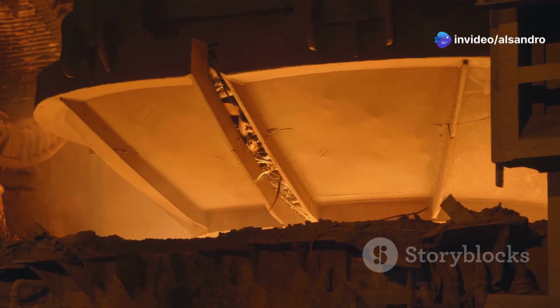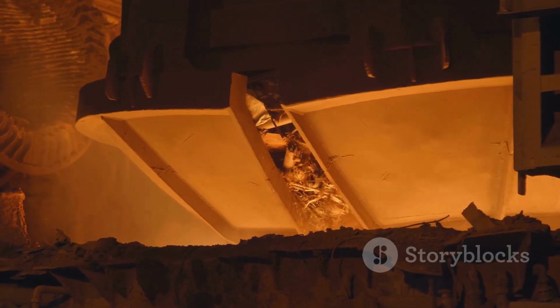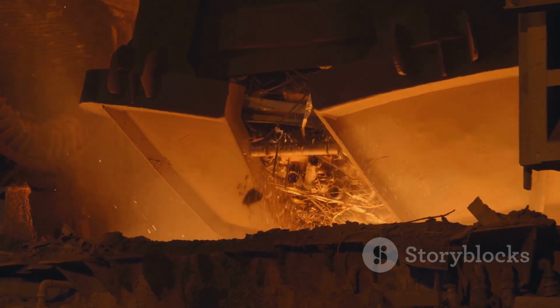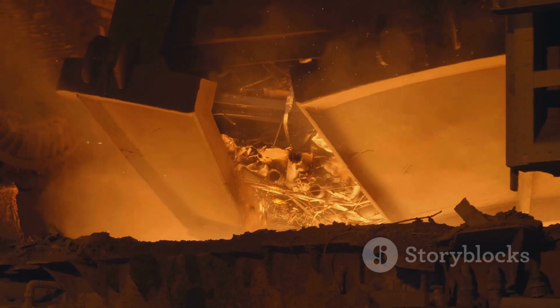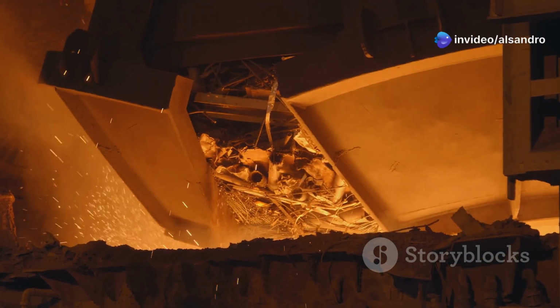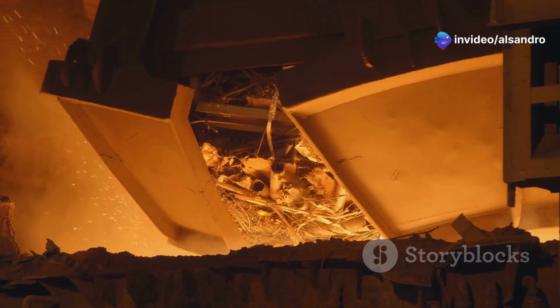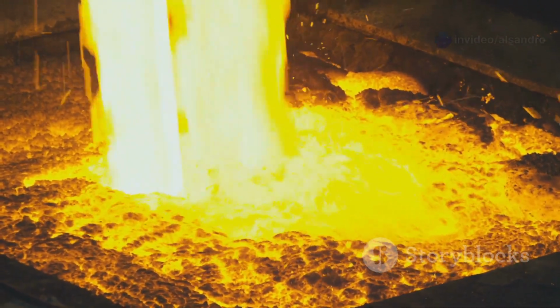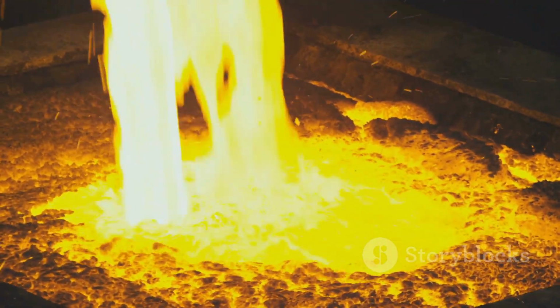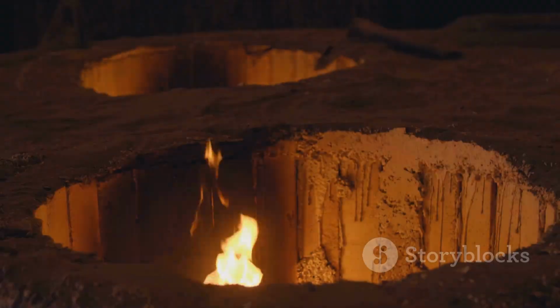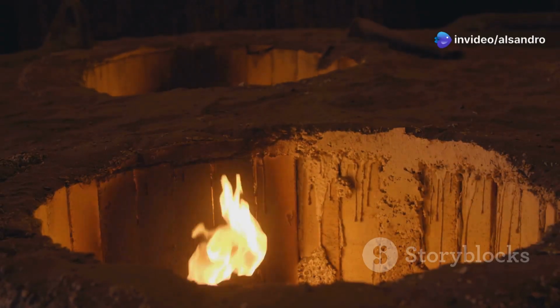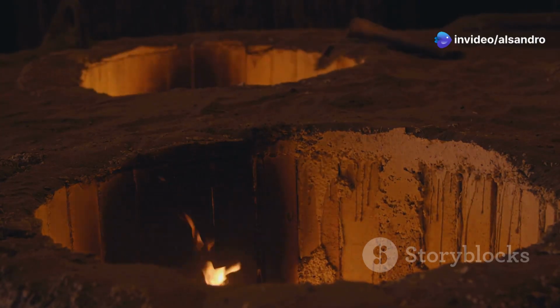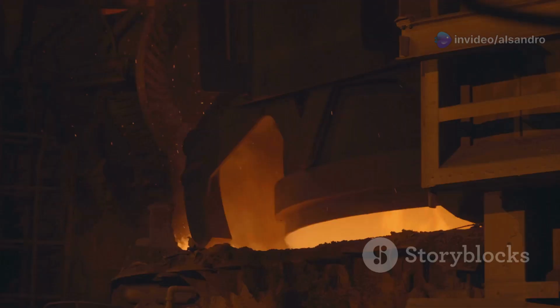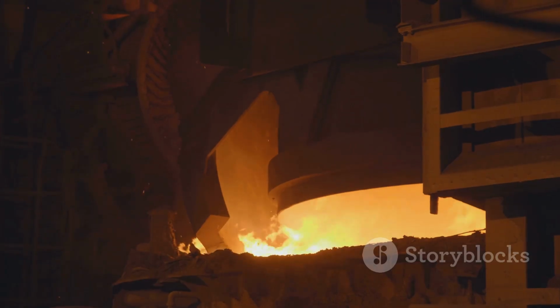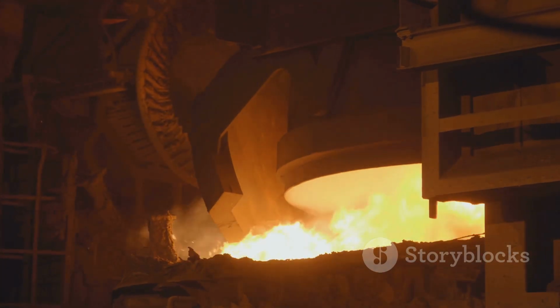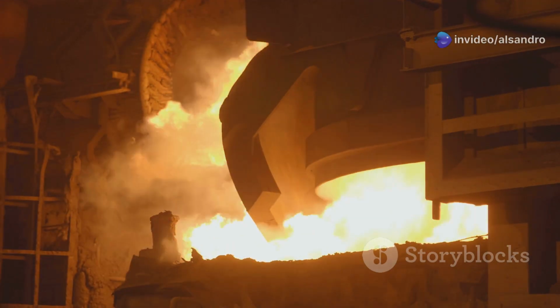Finally, let's not forget about the furnace lining itself, the refractory. This material is designed to withstand incredible heat, but it's not invincible. Over time, the aggressive chemical nature of some slags can actually eat away at the refractory. As the lining erodes, it becomes rougher, creating little nooks and crannies where the slag can get a foothold and start its buildup. The type of refractory, the quality, and also your installation process are important. A lining that is not chemically compatible with the type of slag you are producing will wear out faster and contribute to the problem, creating a vicious cycle of erosion and buildup.